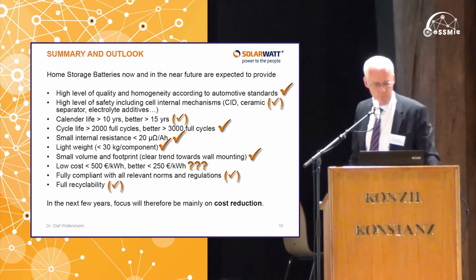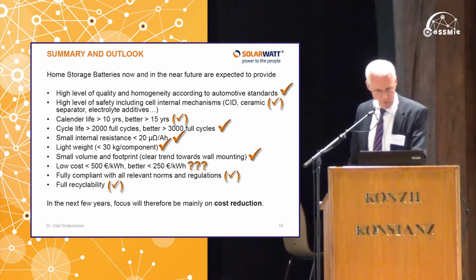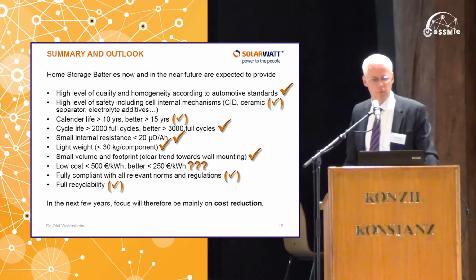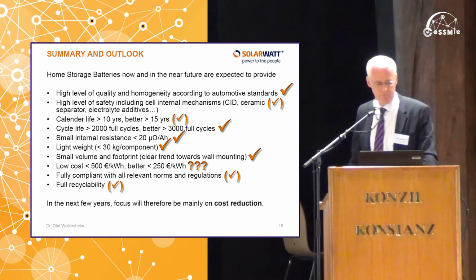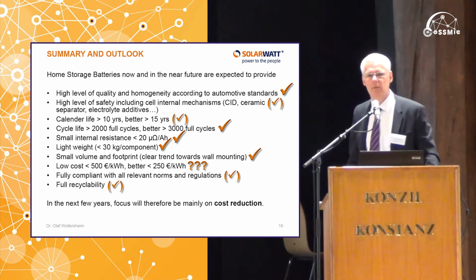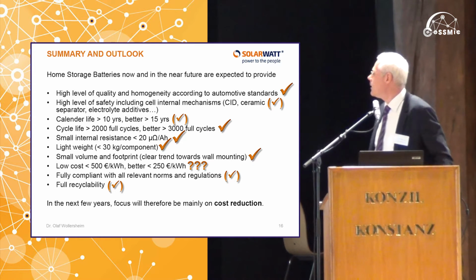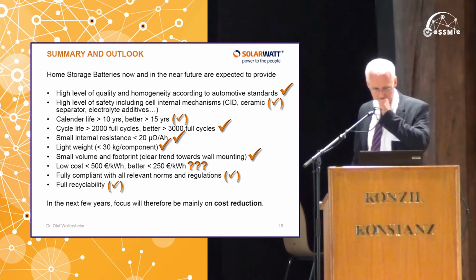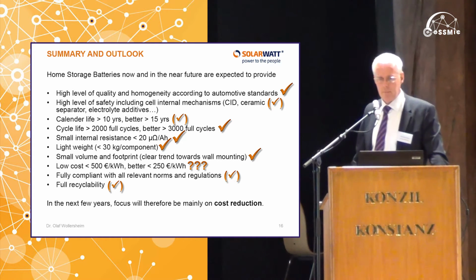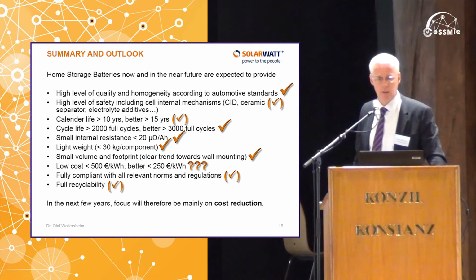The calendar life should be at least 10 years, better 15 years. So this is the life that the cell is providing without being operated. And the cycle life should be better than 2,000 cycles, preferably better than 3,000 full cycles. This would give the customer about 15 years of lifetime. It should have a small internal resistance, better than 20 micro-ohms per ampere hour. It should be lightweight, so the heaviest component should not be more than 30 kilogram.